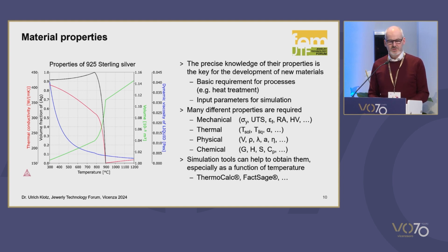And this example here shows some properties of standard sterling silver. So the black curve shows the volume fraction of the solid phase. And you see above 900 degrees, the sterling silver is liquid, the solid fraction is 0, and then it suddenly increases during the melting range. And if you look at the green, the red, and the blue curve, you can see that these curves show significant changes during the solidification. The volume is reduced. This is causing the shrinkage problems that we all know during casting.